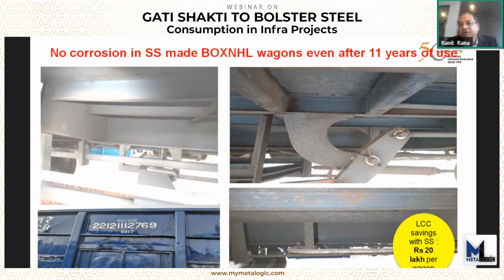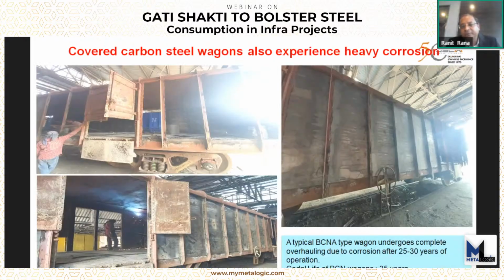And as you can see, this is a wagon which has been used for 11 years. And till now, even after 11 years of service, we can hardly see any corrosion in these wagons. And we have done a very detailed cost-benefit analysis with stainless steel, and the cost savings with stainless steel comes to almost 20 lakhs per wagon, which is a significant amount.